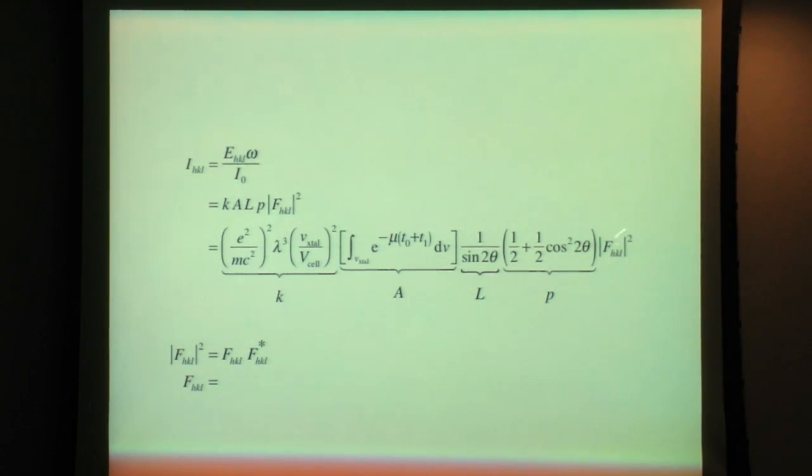And here's our square structure factor amplitude, the product of our structure factor and its complex conjugate. So I'll complete the rest of the story on this slide. The point is we know how to calculate the structure factor. It's the sum over the atoms of the occupancy factor times the atomic scattering factor times the Debye-Waller factor times the exponential of 2 pi i h dot r, or dot x. Okay, so we can know what those structure factors mean.